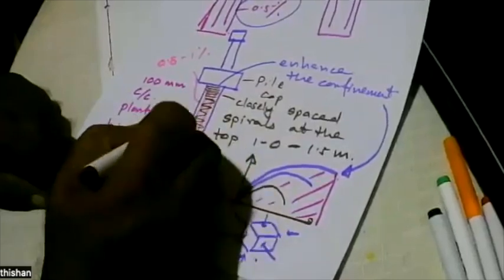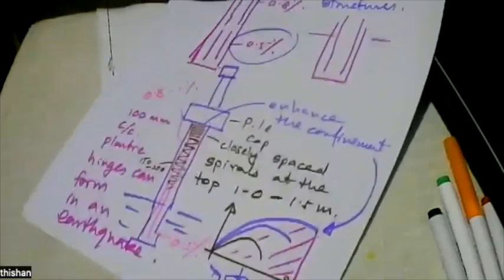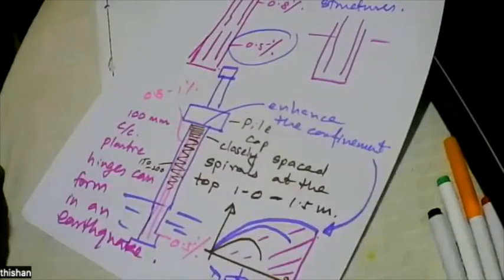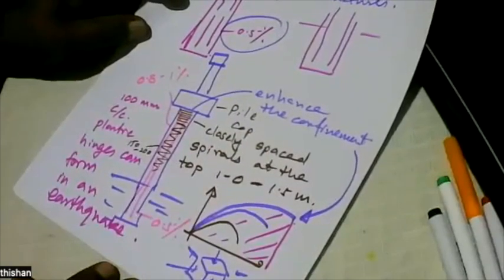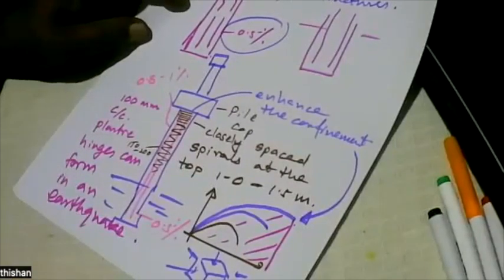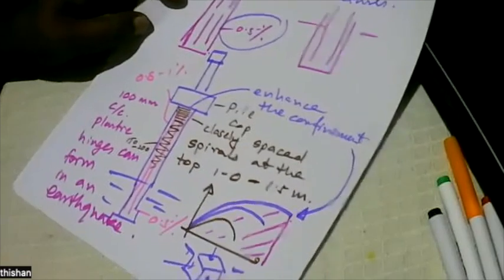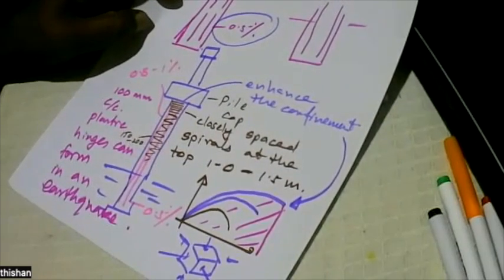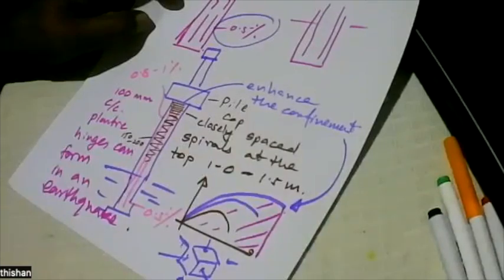And after that, it can be a pitch of 150 to 200, depending on the piling contractor's need. Like the piling contractor will need certain stiffness for the piling cage, the reinforcement cage, and for that stiffness, they might need a certain spacing. But certainly, at the top of the pile, it's good to have a closely spaced spiral, so that this spiral can provide plenty of confinement to concrete, so that concrete will behave like a super strong material, not 30 megapascal concrete, and that will prevent crushing of concrete in the pile at the top, and the bridge might be able to survive the earthquake pretty well. So when you are looking at piles, you have to actually be a little careful.